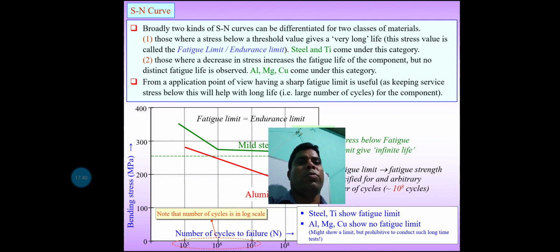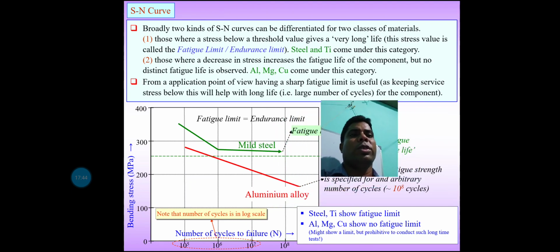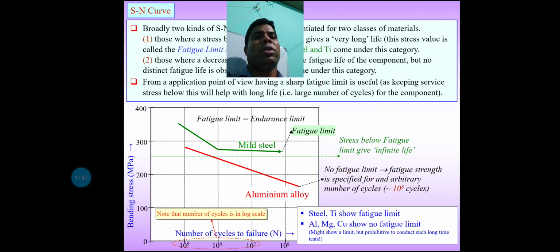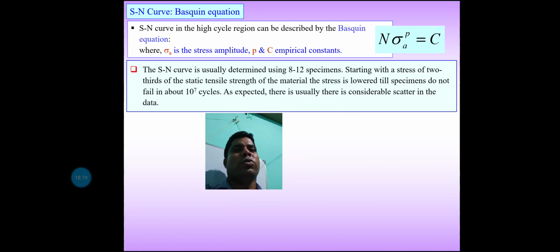From an application point of view, having a sharp fatigue limit is usual, and keeping the service stress below it helps with long life. Here the indication is that fatigue limit is equal to endurance limit, and that case is the top level, the green color indication, which is the mild steel, and the red color is obviously the aluminum alloy. The number of cycles to failure ranges from 10 to the power 5 to 10 to the power 7 cycles. The SN curve Basquin equation is N times sigma A to the power P equal to C, where sigma A is the stress amplitude, and P and C are empirical constants.